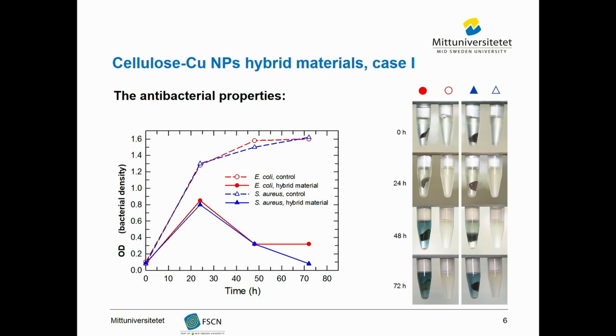As a possible application, we examined the antibacterial properties of the synthesized hybrid material for both gram-negative and gram-positive bacterial strains. We observed that in a suspension containing the hybrid material after 24 hours, almost 40% of bacterial density decreased compared to a control sample without any hybrid material. And on a longer time scale, we see even more reduction in bacterial density, showing that this hybrid material can not only inhibit bacterial growth but also kill bacteria in a short time.